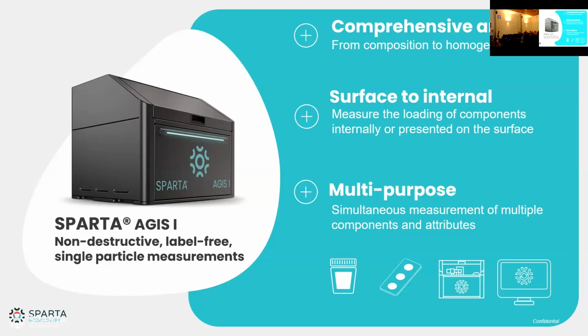If you want to do more absolute sizing, you can. We've done this in a paper before. You can look at displacement of an internal standard basically to calibrate that. Whilst it's technically possible, almost no one uses SPARTA for that because almost everyone already has a DLS, and they already know the size distribution of the particles. But linking that to the composition is something that you can't really do with other techniques, and that's really what we will focus on.